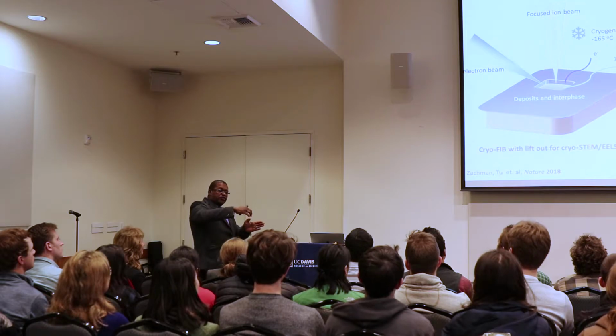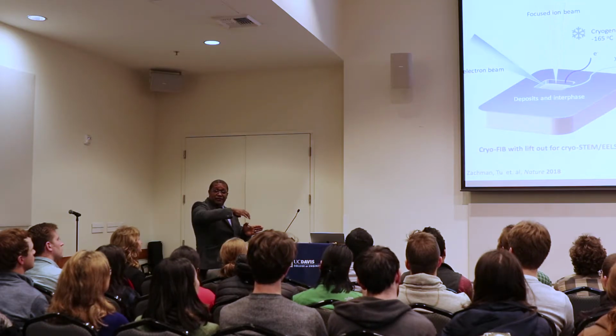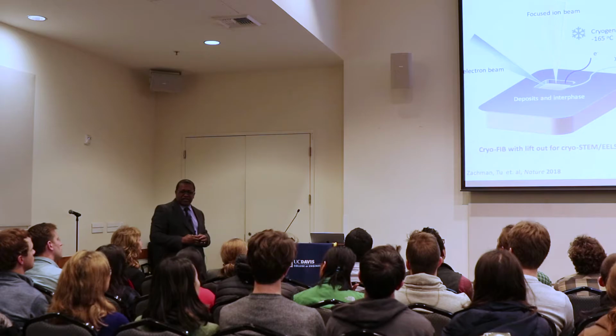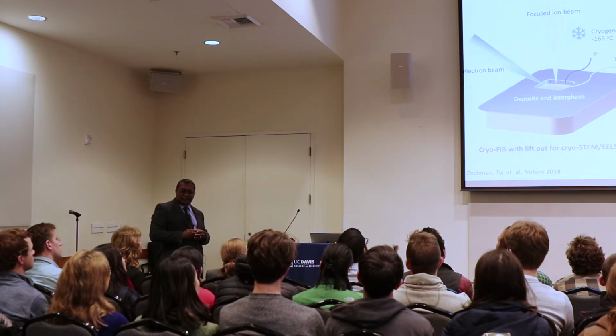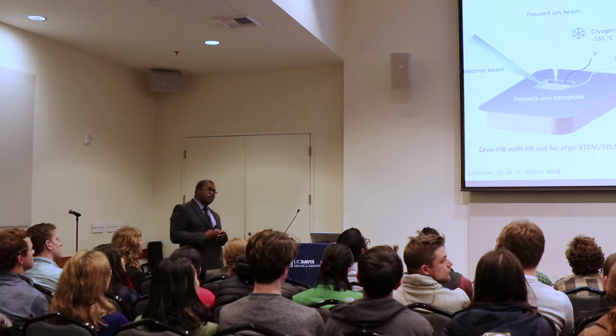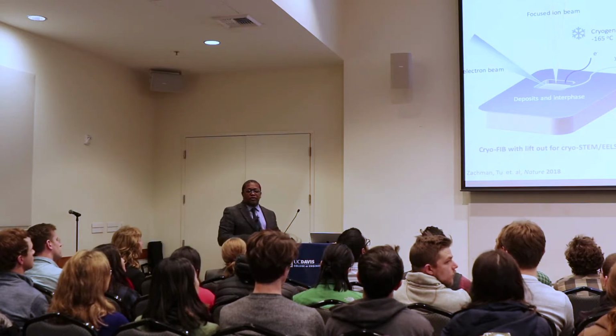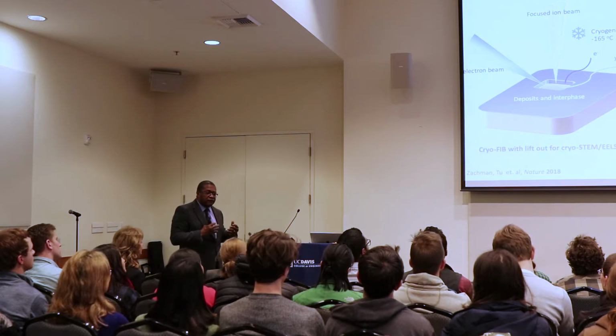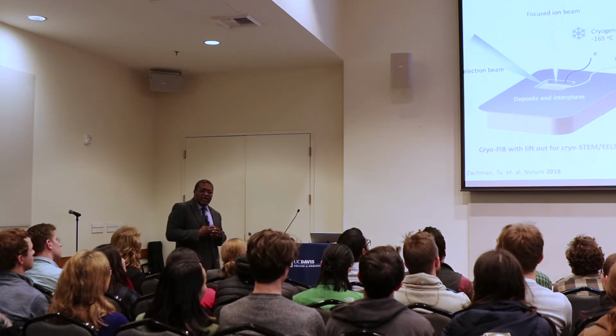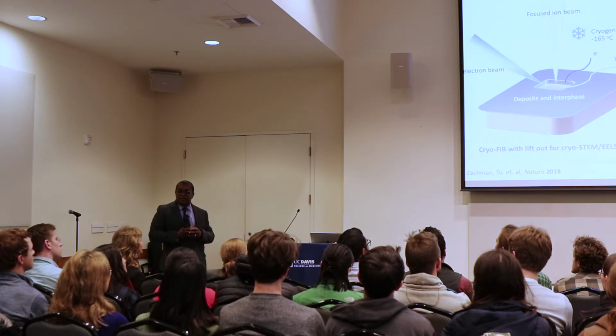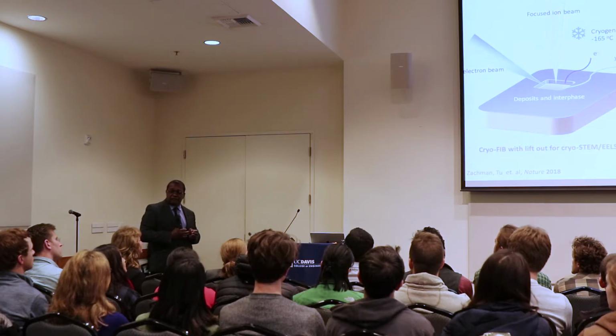That allows us to do scanning electron microscopy in the plane, and basically what we're studying is the out-of-plane characteristics of the layer that's formed on the lithium. Now, because we do this in an electron microscope where we can observe what it is, at the same time we can do spectroscopy like Auger. We can learn about the chemistry of these layers.